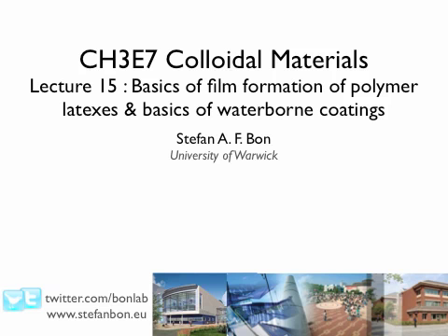Or they're, for example, used as a template to backfill. So one of those pictures, it was backfilled with titanium dioxide, and then you wash away the spheres, and you'll end up with this reciprocal continuous structure with periodic holes in it, which is used as a band gap material quite often in photonics, and which could form the basis of a solar cell type of arrangement. So that's what you can do with hard stuff.